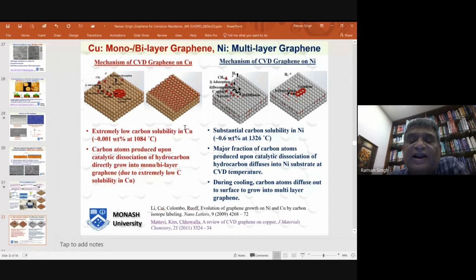Whereas nickel has very high solubility of carbon, as you can see here. So whatever carbon you generate here, it diffuses into nickel matrix, it saturates the matrix, and then when you cool down, carbon is rejected because solubility decreases with decreasing temperature. And again, you have carbon diffusing out, and it develops graphene. And that kind of graphene can be developed as multi-layer graphene. So nickel can develop multi-layer graphene. Copper can develop only one or two layer graphene because copper does not have much solubility. Keep that in mind because we will use that later.